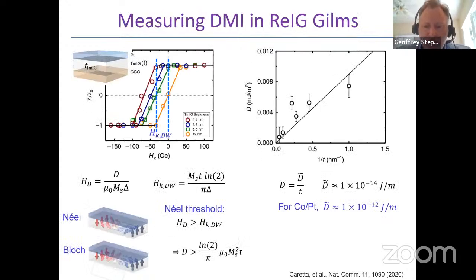But let me come to this point. It turns out that the DMI here is very small. The DMI is about 2 orders of magnitude smaller than what one finds at a cobalt platinum interface. But because of the threshold of DMI that is required to stabilize a Néel domain wall: if you don't have DMI, domain walls tend to be Bloch. And the energy difference between a Néel and a Bloch wall is completely magnetostatic.